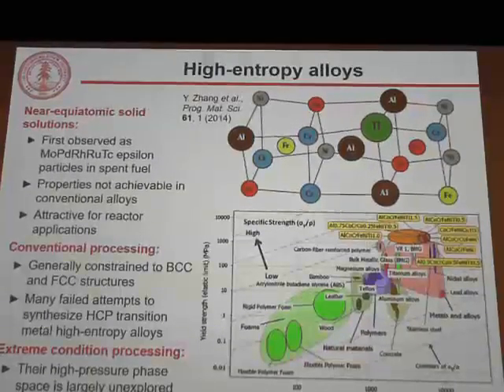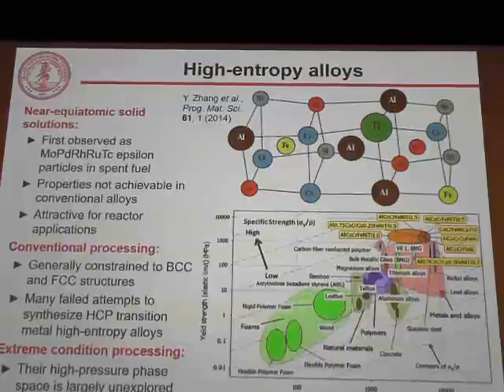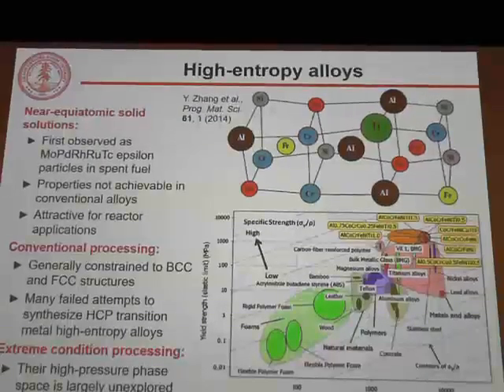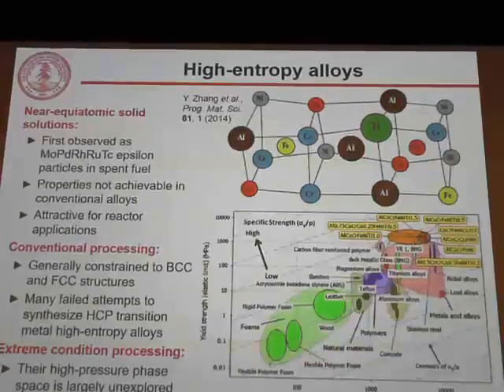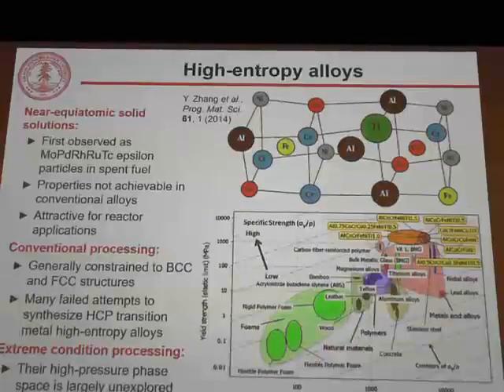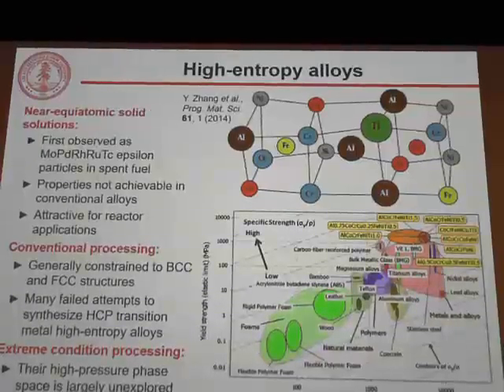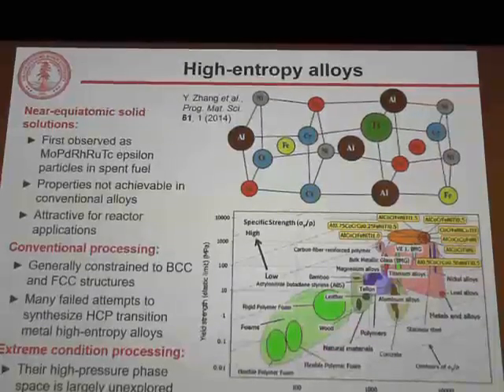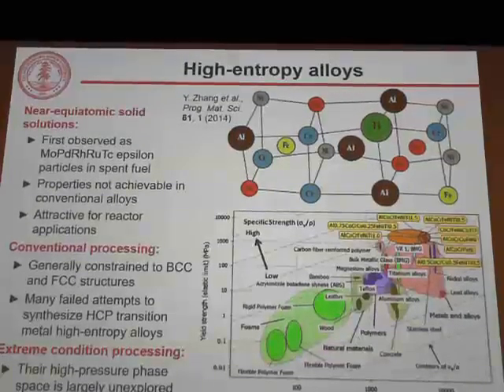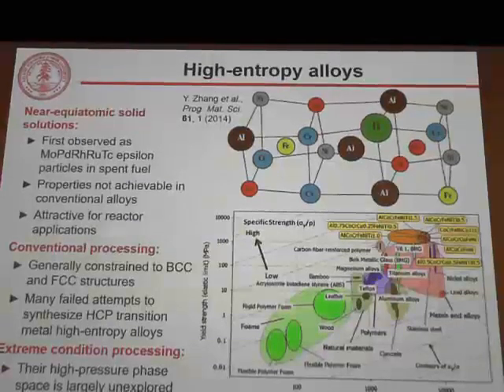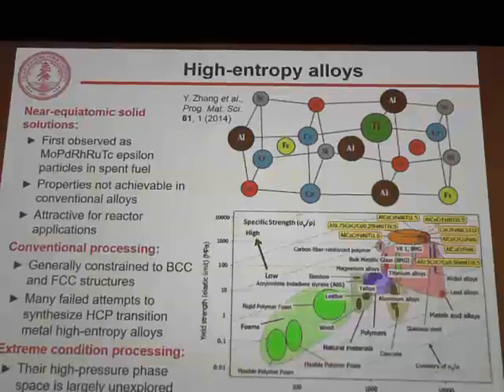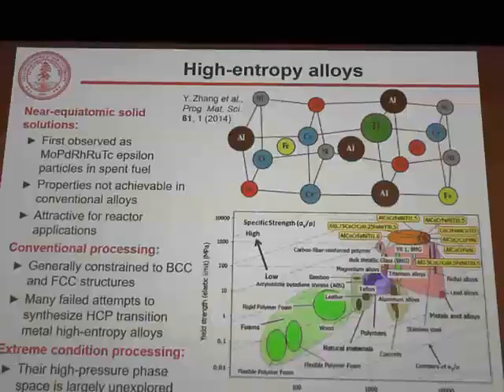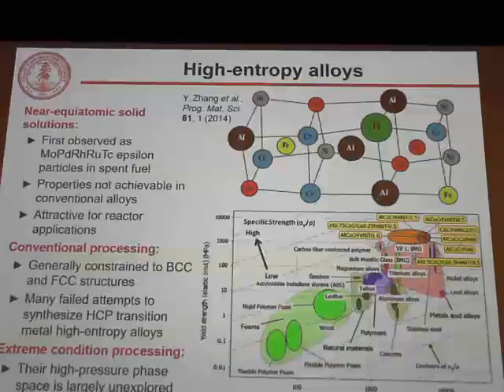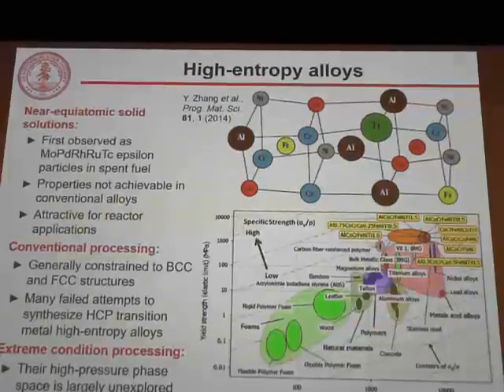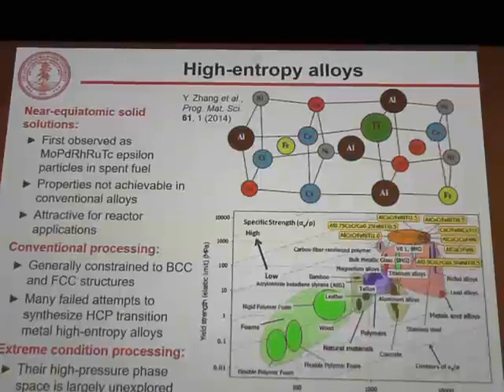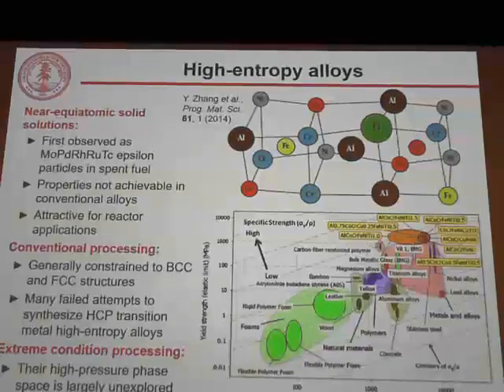However, by conventional processing, we can access only, or typically we can access only 2 phases in these materials, body-centered cubic and face-centered cubic structures. That's true of most transition metal high entropy alloys, which are those that might be used in reactors. And this is despite many attempts to make hexagonal close-packed high-entropy alloys, which have failed. However, their processing by extreme conditions has not been pursued previously. So there's an opportunity here to look at, for example, the high-pressure phase space of these materials and see if we can make this unique HCP phase.